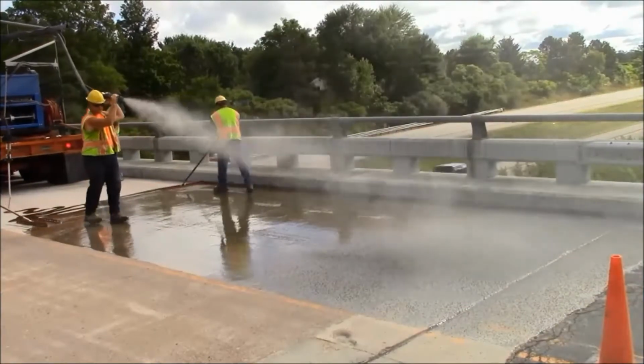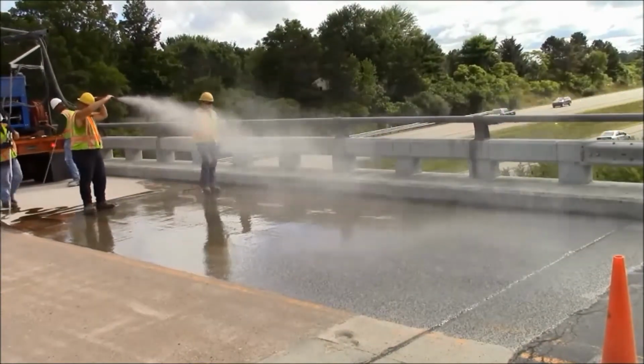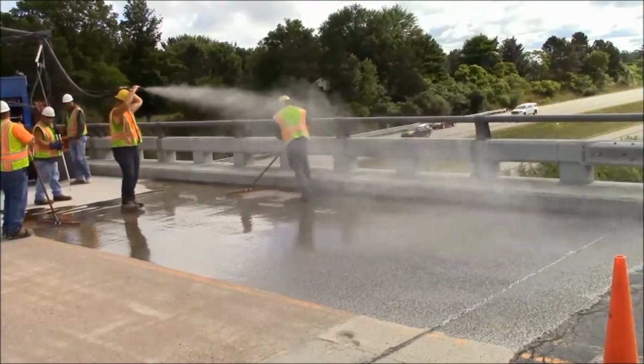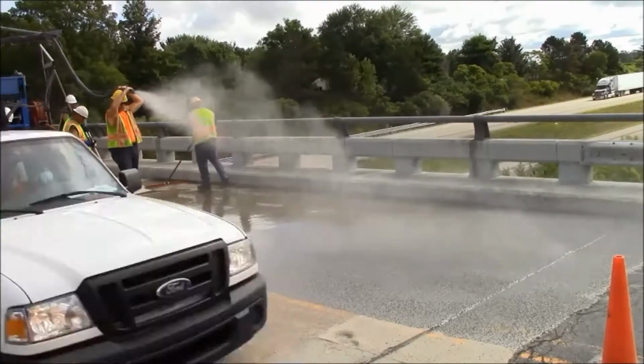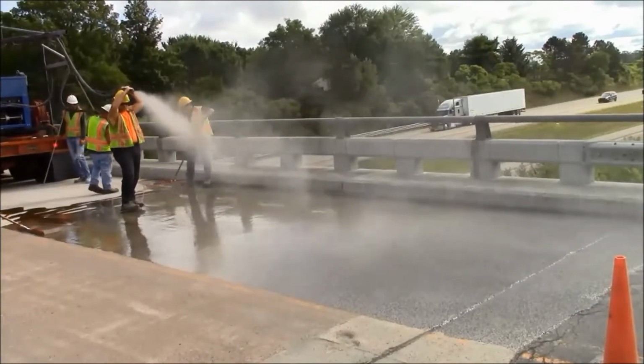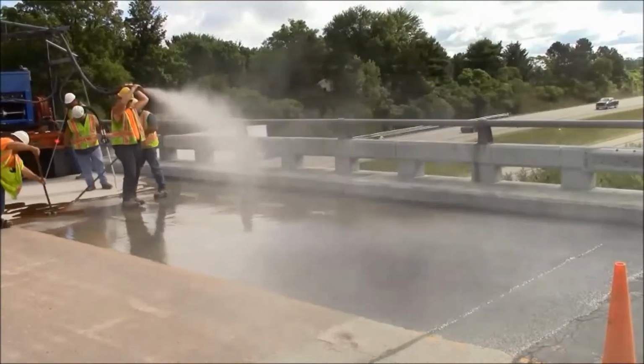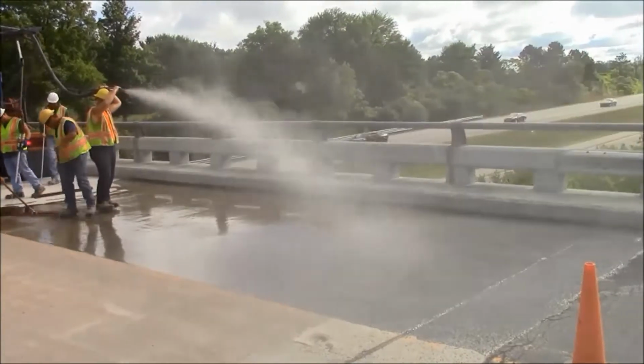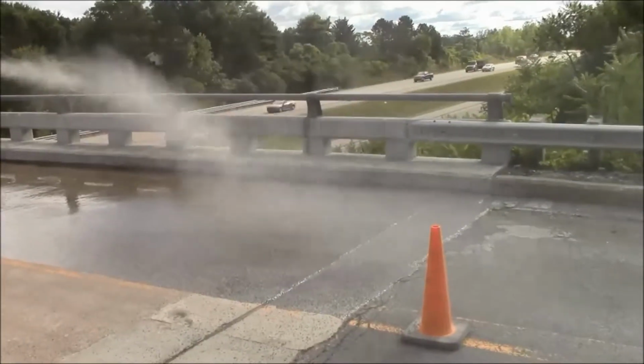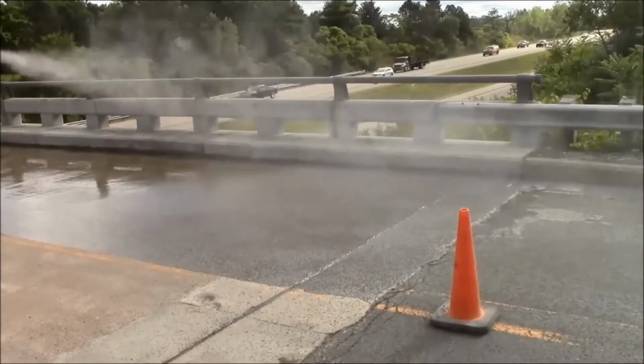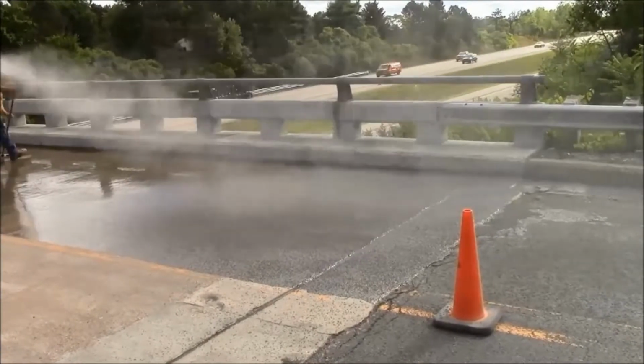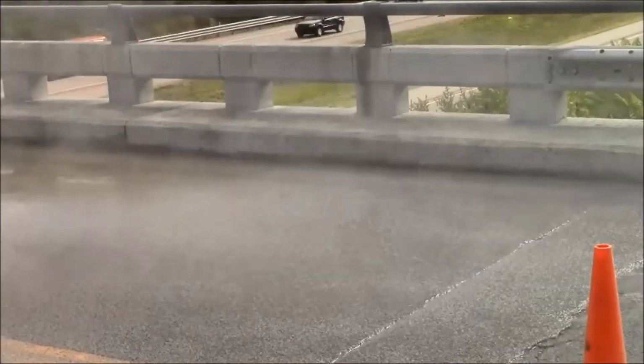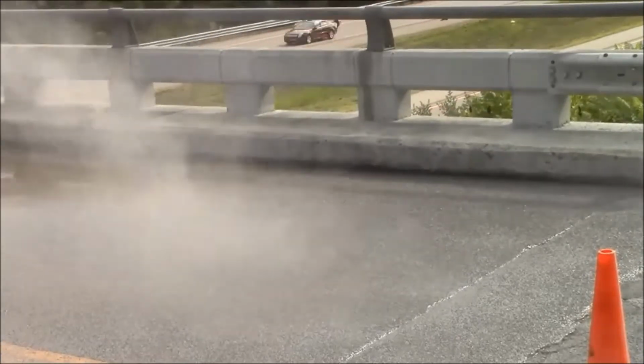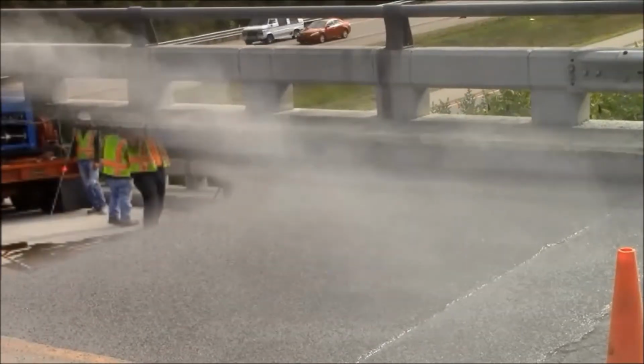For this operation, the contractor has elected to use a pneumatic blower to broadcast the aggregate. It is important to cover the wet resin binder to refusal before it begins to cure and thicken in viscosity. The aggregate will fully embed into the resin binder at this time. Waiting too long can cause early loss of aggregate, especially within the wheel path. A loss of friction in the wheel path can become a safety hazard.